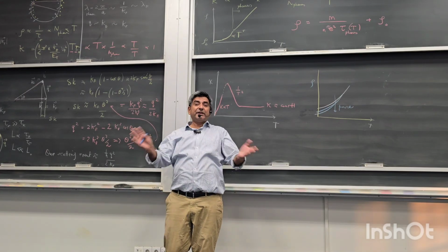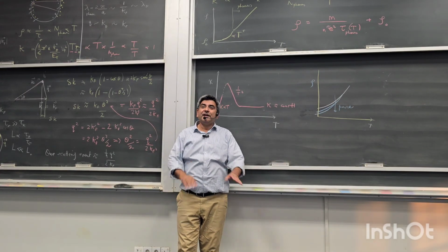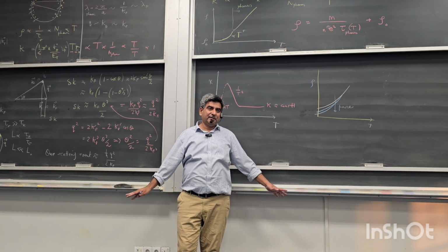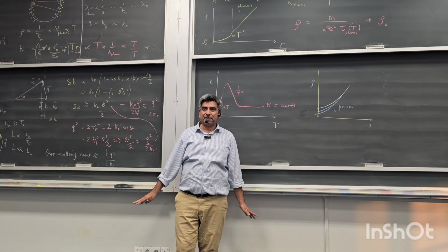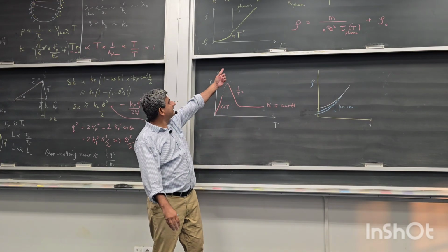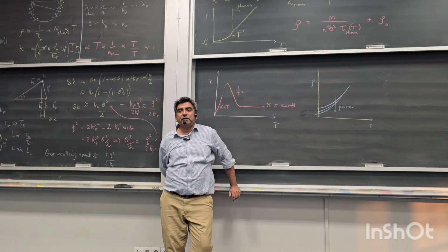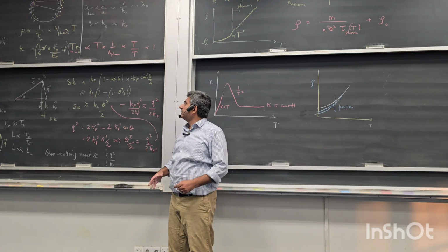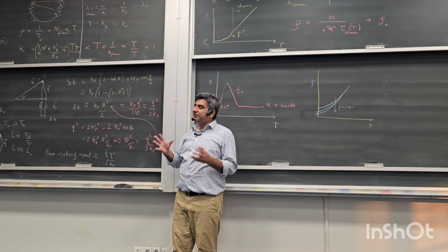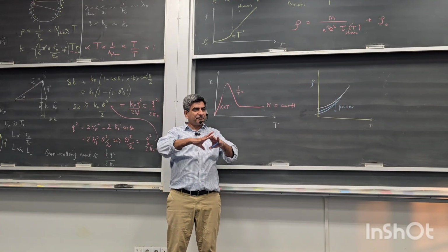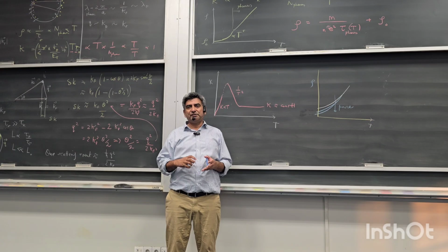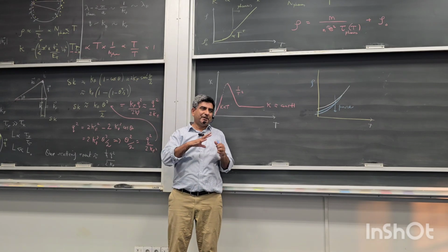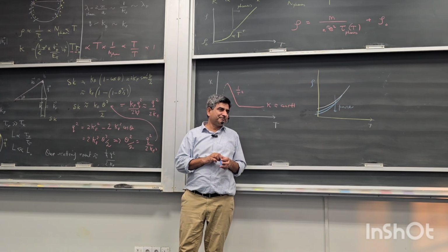But in most cases, that's a very good approximation, as I'm going to describe in a minute. Electron collisions have a very little impact. But sometimes they do. There are other reasons why this T raised to power 5 dependence does not manifest itself. For example, one reason is that the Fermi sphere generally is not a perfect sphere. The Fermi volume for electrons inside metals takes this very complex shape. I'll probably show some of these shapes tomorrow.